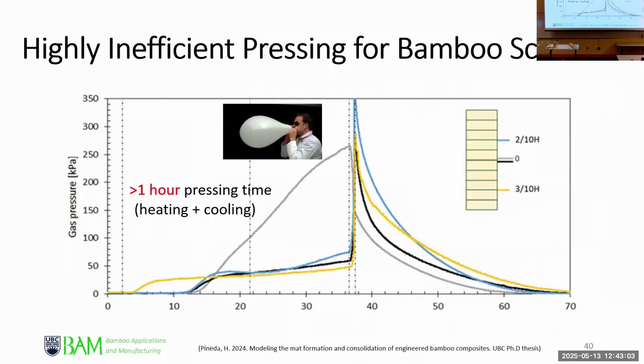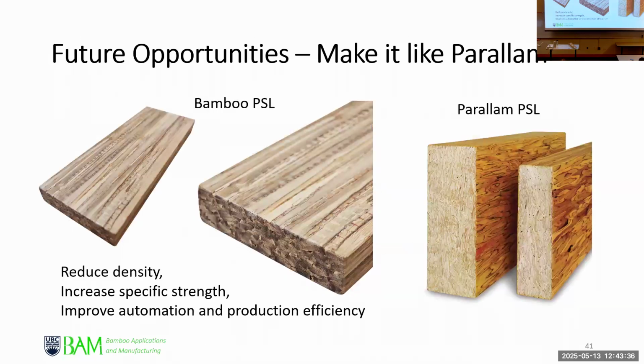And in that process, the hot pressing is a real problem because it takes so long. This is looking at the pressure, how the gas pressure is building up inside the product. And you have to release that pressure before you open it. Otherwise, you're going to have the blow or the delamination. So that process takes over an hour, which is really a problem when it comes to